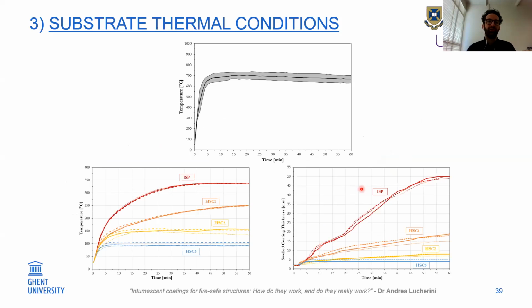What you can see again is that in terms of the surface temperature, since I applied 50 kilowatts per square meter, the temperature at the surface tended to steady state conditions, between 650 and 750 degrees Celsius. But by having different thermal boundary conditions at the back, I have different temperatures in the steel substrate. This is the case of the insulated steel plate, so all the heat gets into the plate and I achieve a temperature of about 350 degrees. Then I have 3 different cases where I changed the water flow inside my sample holder to get a different temperature in the steel. In heat sink case number 1, a low flow rate of water, I got a temperature of about 250. With a higher flow rate, I got about 150. And in the third case, I got about 100 degrees.